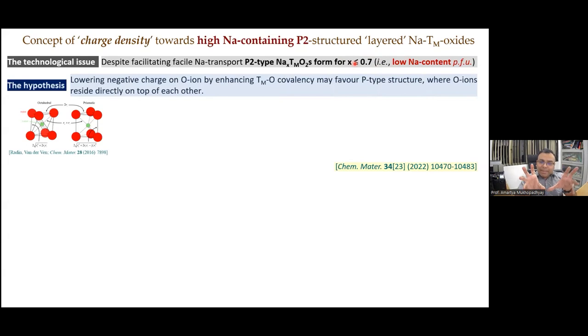Now, if we want to retain the P prismatic coordination, that is, have the P-type structure stable, while at the same time we want to increase the sodium content, let us first look at the octahedral versus prismatic coordination closely. This schematic is from a well-known paper by Radin and Van der Ven, and it clearly shows that for an octahedral coordination, the oxygen ions are displaced from each other. I mean that the oxygen ions are not directly sitting on top of each other in an octahedral coordination, whereas in a prismatic coordination, the oxygen ions are sitting directly on top of one another. So if the effective negative charge on the oxygen ion is more, they will not like to sit on top of one another. Rather, they will prefer to be displaced with respect to one another and take up an octahedral coordination as opposed to prismatic coordination.